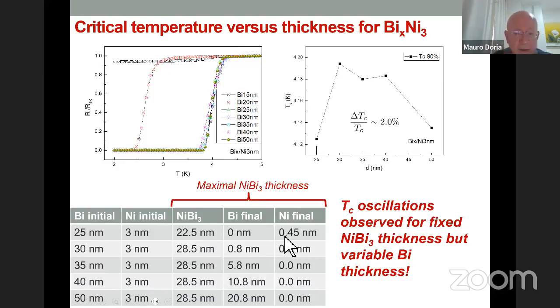So you have some final bismuth layer and no nickel left. Here, in the first one, we have some nickel left. In fact, there are things that are not understood here, because nickel is magnetic. What is the effect of nickel on the final compound? Even with nickel bismuth 3, you have some magnetism nearby. It's not clear. When you look at 20, the critical temperature is even much lower, so it is not even in the table, nor is 15. So we select the data to see if these oscillations are trying to tell us something or not. Currently we're doing some measurements on nanoparticles to see such effects. That's the answer to your question, to the best I can do.